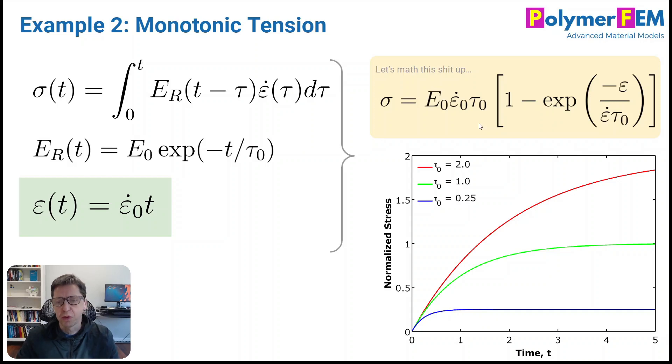Is that what you expect for a polymer? Usually it's not what you expect. It depends on the microstructure of the material. You can also see if you take the derivative of stress with respect to strain that a lot of things cancel out and you get E0 back. So that initial slope here is E0 and the final value is given by this. Kind of interesting, perhaps, but that's something that comes right out of these equations.